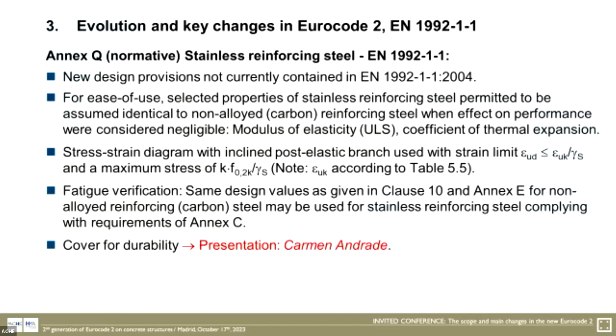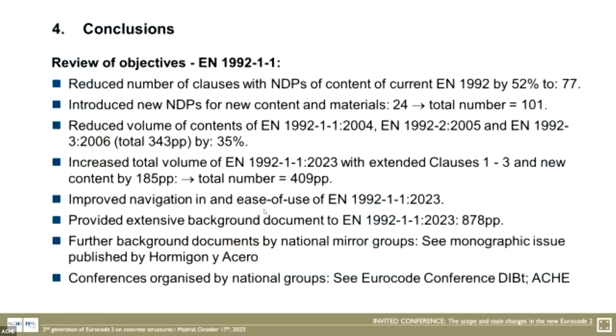so the same stress-strain diagram. I'd like to highlight that at the maximum strain, we cut for stainless steel at the same strain values as we specified for non-alloy reinforcing steel, even though stainless steel may have larger ultimate strain capacities. And we permit to use the same provisions for the same limits for fatigue as for non-alloy reinforcing steel if the steel complies with Annex C.